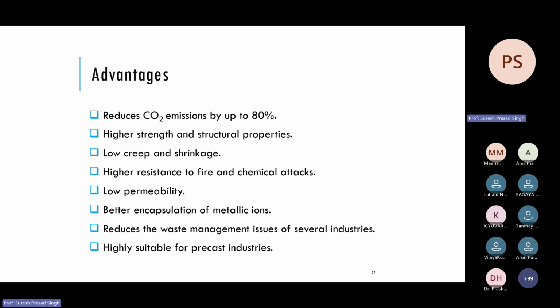Because as I told, most of the raw materials we use are industrial waste or industrial byproducts, and they contain metallic ions, heavy metals, toxic elements and all these things. The geopolymer structure encapsulates the harmful metallic ions. Otherwise, they will be leached to the surroundings and create an environmental impact. So a good encapsulation of the ions occurs, which reduces the waste management issue. It is also highly suitable for the precast industries because it is a very fast setting material.